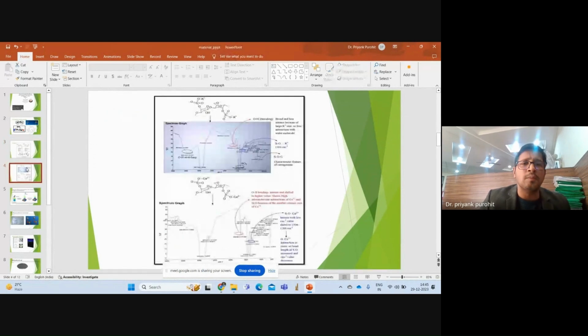The problem with potassium, calcium and sodium is that they are hydrocolloids. If you see in the IR, we checked that OH bonding and OH stretching both were present. It means that water is present in both cases. So we thought to make a hydrophobic polymer which can be used for the entrapment of hydrophobic drugs and other things.